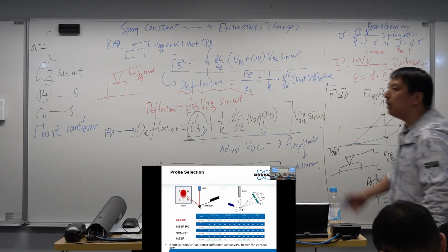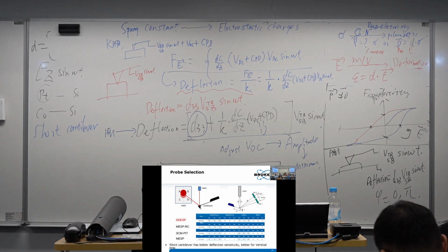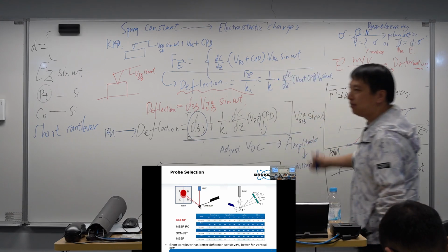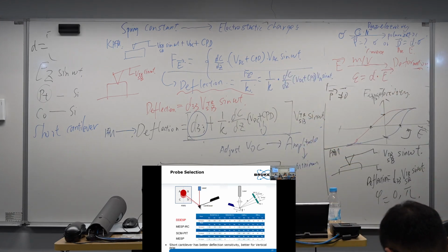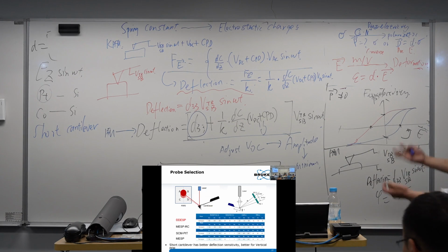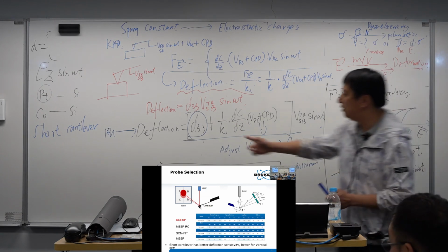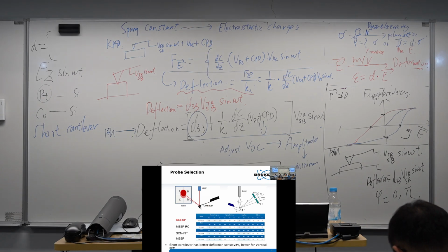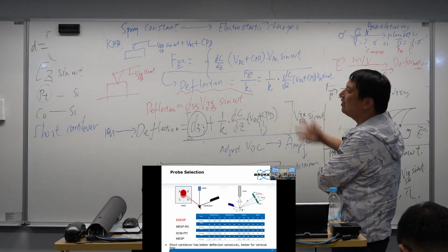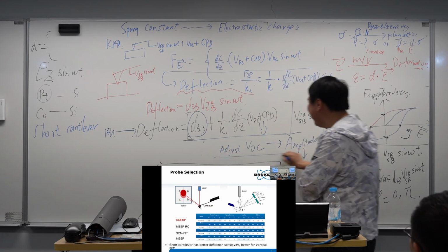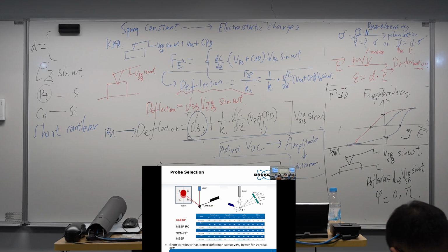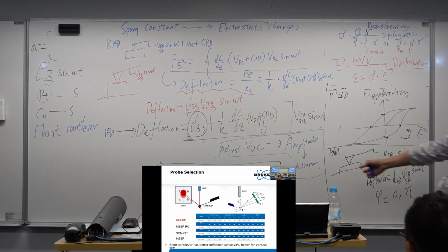Right? The KPFM is easy. The KPFM is adjust the VDC once the amplitude is 0. But today I'm doing the PFM, I cannot make it 0 because there will be a D33 term here. Currently we don't have this, okay? In future, if someone invents this way, yes, that's the algorithm here.